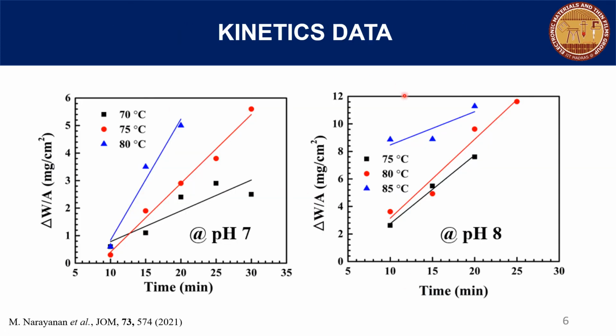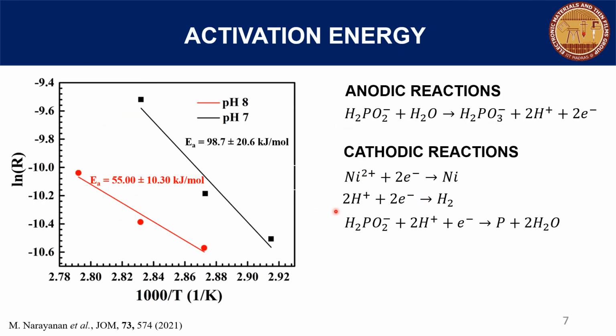To study the kinetics of the deposition process, weight gain versus time was plotted. The graph shows a linear behavior indicating that the kinetics of the reaction is surface limited, and as the pH increases, the rate of reaction also increases. Using the kinetics data, we are able to extract the activation energy for the deposition occurring at pH 7 and pH 8. The activation energy is around 98.7 kilojoules per mole at pH 7, which reduces to around 55 kilojoules per mole at pH 8.